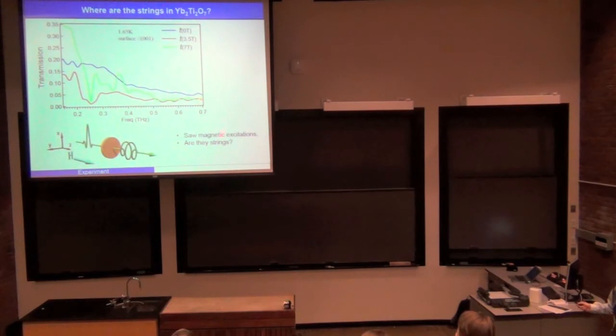So we did some data look at the transmission as a function of magnetic field at low temperature. And if you look at this zero field data compared with the data taken at 3.5 Tesla and also the data taken at 7 Tesla, there's obviously some changes happening. So we are pretty happy. We see some field dependence, and there are a couple of dips in the spectrum. We see, well, maybe we're seeing some strings. But obviously we need to look closer to make sure whether or not there are strings.